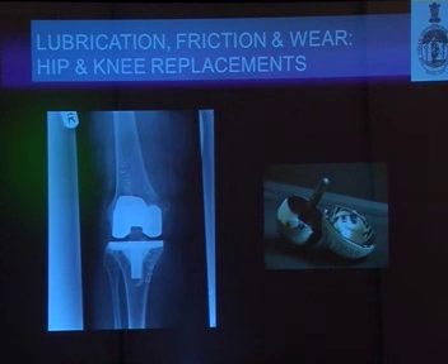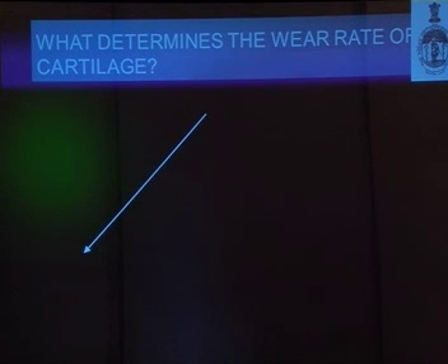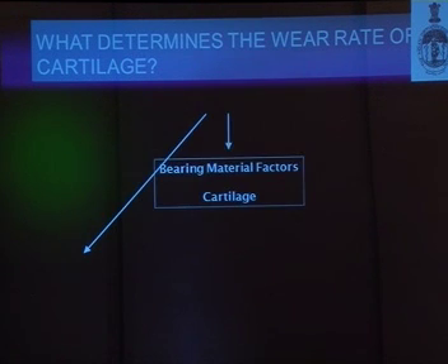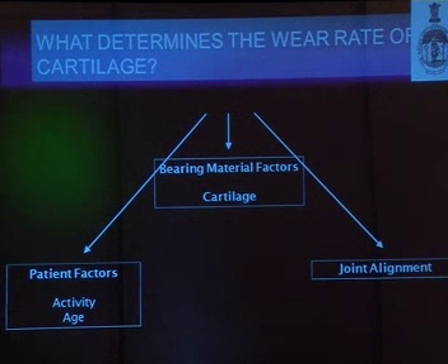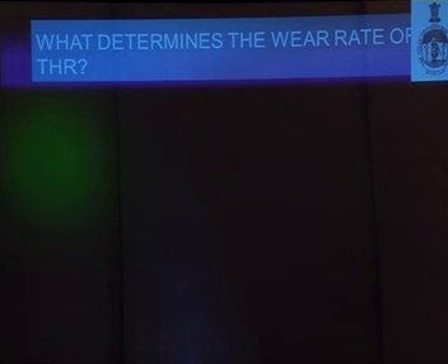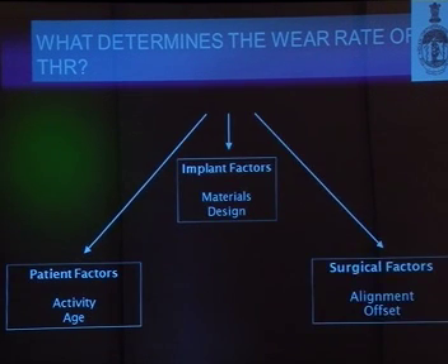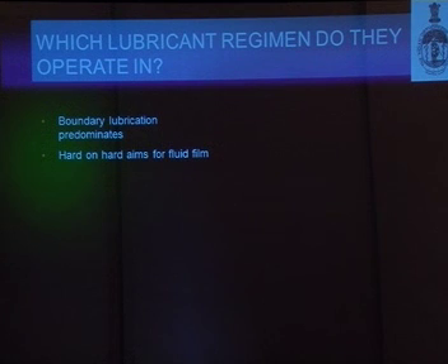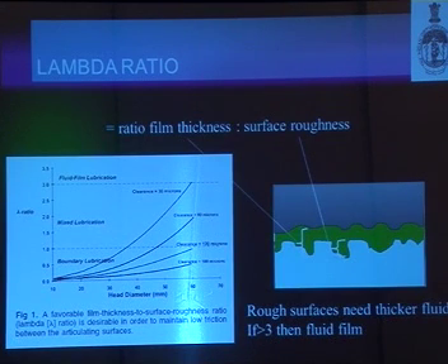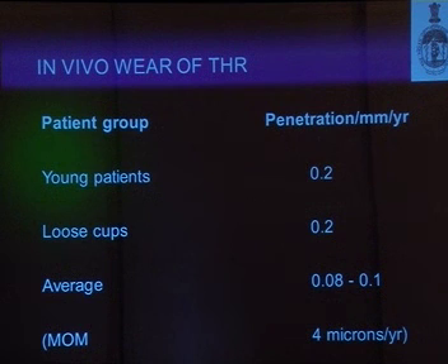So what's the method of lubrication, friction of wear, and hip and knee replacements? What determines the wear rate of a cartilage? Patient factors, activity or age, the bearing material factors, the cartilage, and the joint alignment. The boundary lubrication is normally what operates in the articular surface. The hard on hard surface, like a metal on metal, is more of a fluid film. The in vivo wear rate of a THR is about 0.2 millimeters per year in young patients. For metal to metal, it's 4 microns per year.